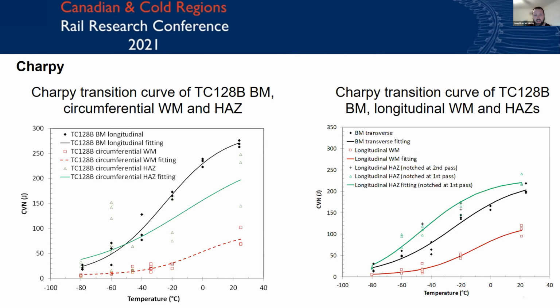So I'll start with the left-hand side of the screen, which shows a figure of the circumferential material weld properties. The base metal is in black on the top, and you can see that as the temperature decreases, the Charpy impact toughness decreases as expected. The circumferential heat affected zone is in green below that curve, and then way down below that is the curve for the circumferential weld metal. So the impact energy, the CVN number for the weld is substantially lower than that of the base material. The trend for the longitudinal welds is generally similar to that of the circumferential weld.